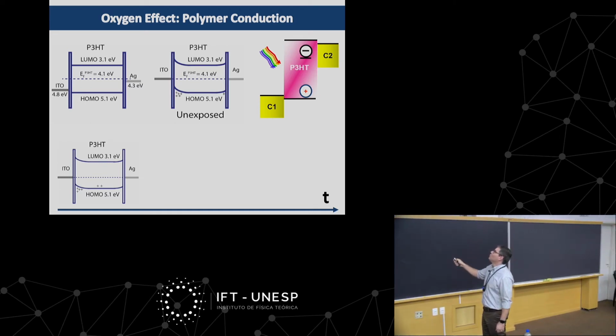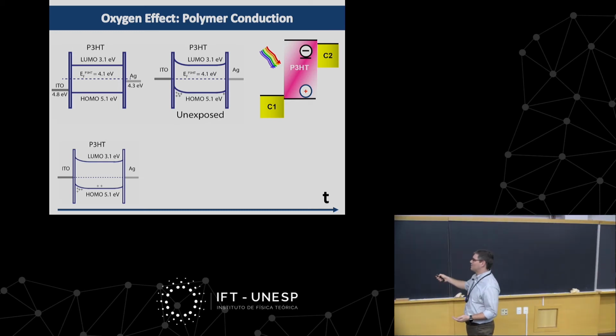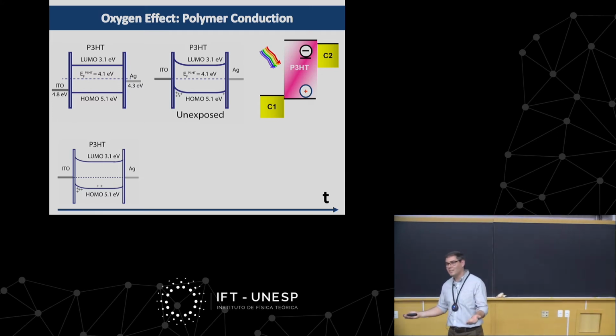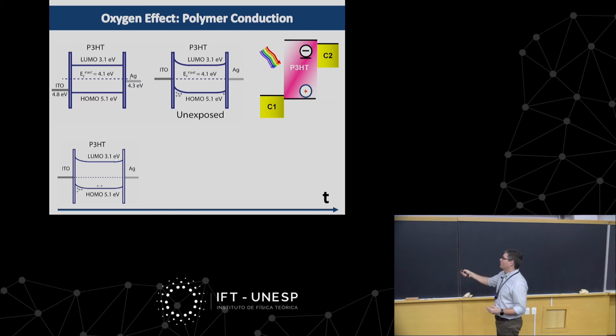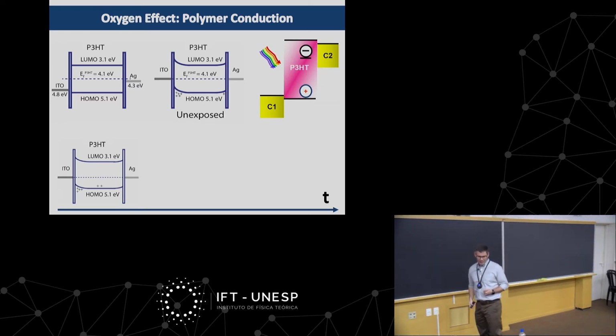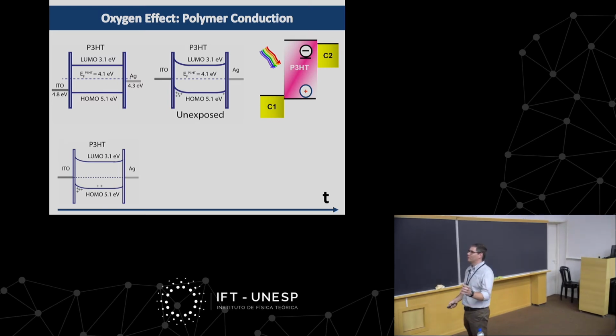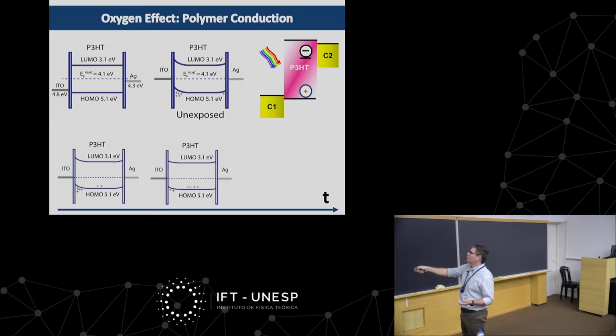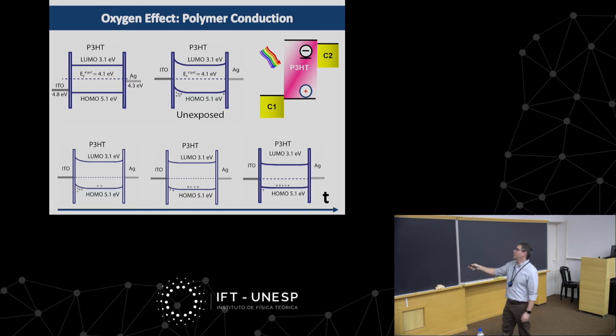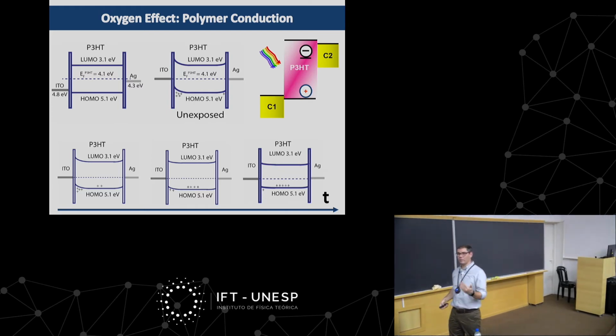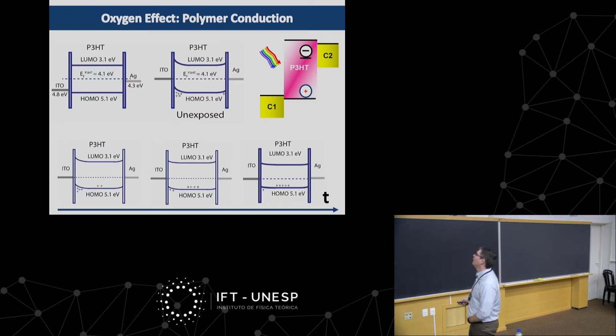The Fermi level moves towards your HOMO, towards your valence band. And by moving towards the valence band, the gap of energy here, that was creating that reservoir, is getting smaller and smaller, and therefore this reservoir gets smaller in terms of charge density. So by doping I get rid of this interfacial reservoir of charge. And this is what happens. As exposure time goes on, I create more doping charge, and the reservoir gets less and less charge. And that explains the type of behavior that I saw on the screen of my oscilloscope.